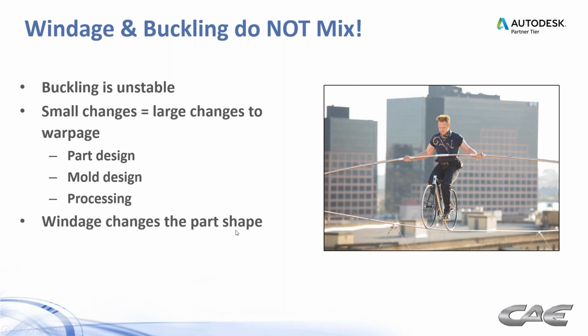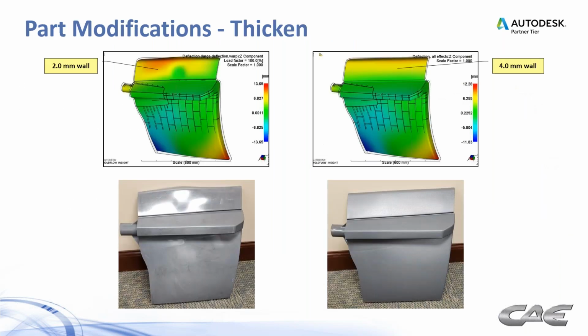Because windage essentially changes the part shape as it sits in the mold. So if we are going to use windage, we need to stabilize the part first, and we're going to use Moldflow to do that. As this example shows here, there's still some warpage left in this part, and if we had gotten to this before the mold was built, the thickness change was a relatively easy change to make, but to put windage into a tool after the tool's already built is a much more difficult situation.